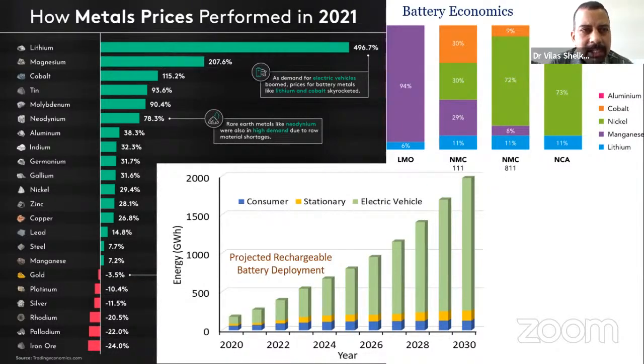And in the last year itself, there has been a 496% increase in the cost of lithium. That is mainly because of the boom in electric vehicles or e-mobility. The cost of magnesium increased by more than 200%. Cobalt, which is already very costly, has registered an increase of more than 100%. And this is the situation in 2021, when the battery deployment is around 200 gigawatt hours worldwide. By the end of this decade, the battery deployment is going to increase up to 2000, meaning a 10 times increase in battery deployment.